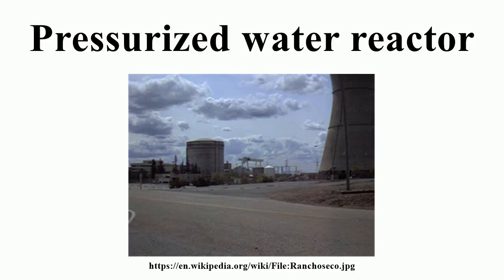In contrast, the RBMK reactor design used at Chernobyl, which uses graphite instead of water as the moderator and uses boiling water as the coolant, has a large positive thermal coefficient of reactivity that increases heat generation when coolant water temperatures increase. This makes the RBMK design less stable than pressurized water reactors.